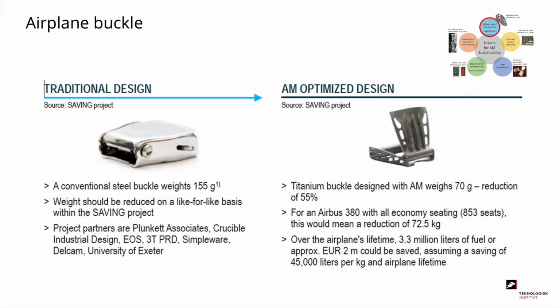One of the really traditional cases I have here, it's from a European project where they optimized some aeronautics components. And we all know this belt bucket from an airplane. The traditional one weighed about 155 grams. Using AM and optimization, it could be reduced to 70 grams. There is a large number of these on a plane, and if you multiply with that and you see how much fuel is actually used per kilo, you can see that over the airplane's lifetime you save 3.3 million liters of fuel. So that is one of the reasons why the automotive and the aeronautics industry has really adopted additive manufacturing, because you can make these lighter components, thus saving a lot of energy, a lot of fuel, and a lot of money.